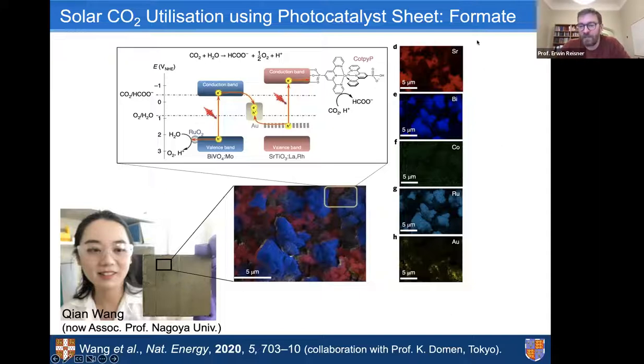You can see from the elemental mapping that really all the elements and components are present. So we have the strontium titanate and the bismuth vanadate, we have the cobalt and the ruthenium catalyst, and also the gold connector that transfers the charge is present on this photocatalyst sheet.